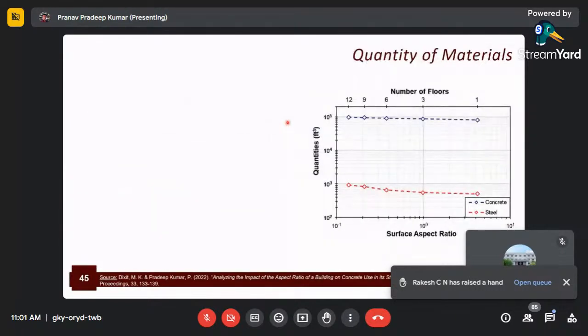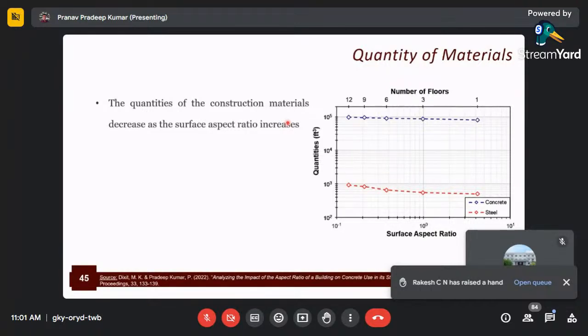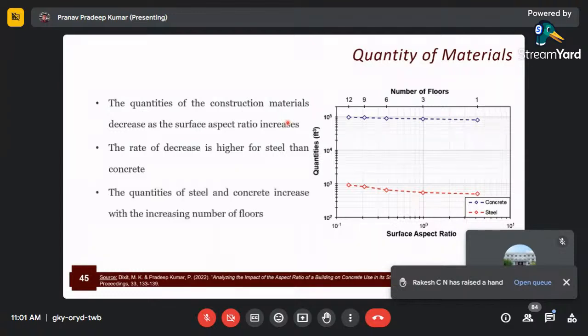So coming to the material quantities that were quantified at the end of the analysis, the graph here shows the results obtained after the structural analysis. From the graph, it may be observed that the quantities of the construction materials decrease as the surface aspect ratio increases, or we could say that as the height reduces, the quantity of materials required also reduces. And the rate of decrease in quantity is observed to be higher for steel than concrete. Also, due to the inverse relationship between the floors and aspect ratio, there is an inverse relationship between the material usage and number of floors.